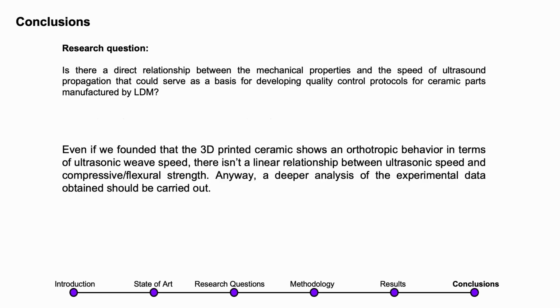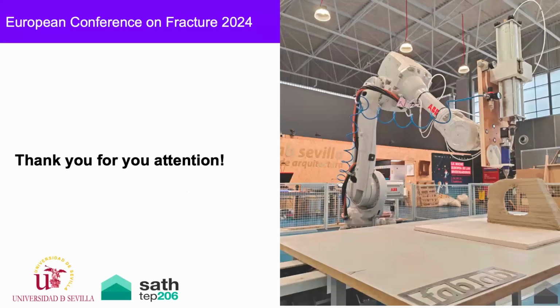And for the purpose of finding a non-destructive quality control protocol, even though we found that the ceramic shows orthotropic behavior not only in the mechanical tests but also in the ultrasonic wave speed, we didn't find a linear relationship between the two tests, so we need a deeper analysis of the results to try to find that relationship between them. And that's it. Thank you.